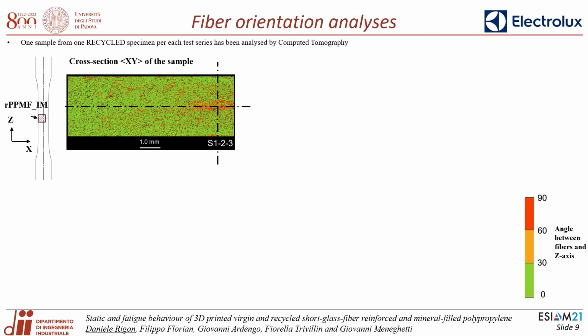By means of computed tomography, we have also analyzed the fiber orientation only for the recycled material. From the IM specimens, one sample taken from the gauge part of the specimen was analyzed. The color image reports the cross-section of the specimen indicated by the center lines. The color bar reporting the colors related to the angle between the fibers and the z-axis or load direction is reported in the bottom right of the slide. As you can see, in the IM specimen, there is a part in the core of the specimen with the fibers oriented between 60 degrees and 90 degrees with respect to the load direction or z-axis. In the remaining part, the fibers are overall parallel to the load direction.